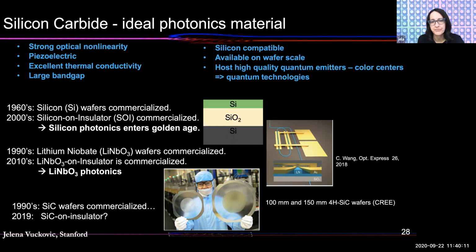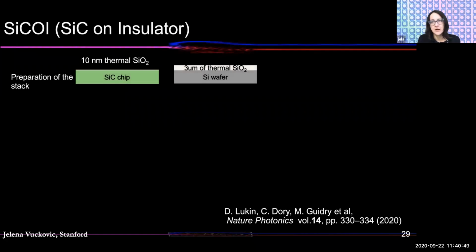And I'd like to mention that, if you're interested in nonlinear optics, silicon carbide is a material that is much easier to process than lithium niobate. And its second order nonlinearity is maybe a factor of about 3 lower than for lithium niobate, but you can very easily compensate for that difference in chi2 by making high quality photonics, as I'll show you in a moment. So I really think that silicon carbide is an ideal material, and on top of everything, it hosts really high quality qubits. So how do we make silicon carbide on insulator?